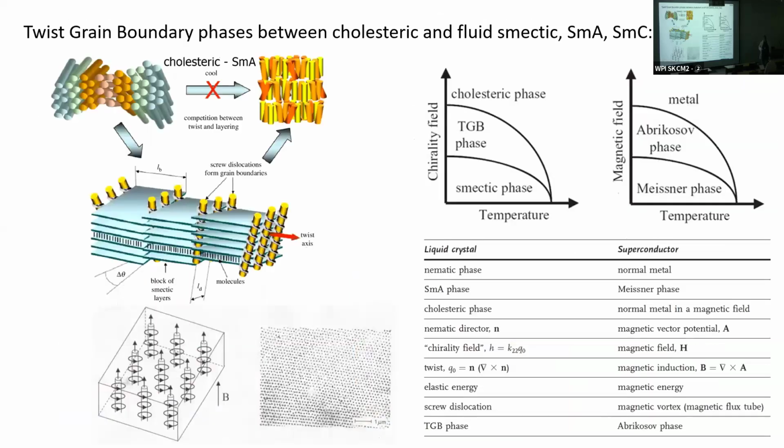Okay, so the other, yes. Are they stable across a large range of temperature? Well, that was the idea, yes. That's the point of using polymer stabilization, is to widen the phase existence range. Because otherwise you would have to heat your display and keep the temperature constant at exactly 48.7 degrees. And that's not feasible.